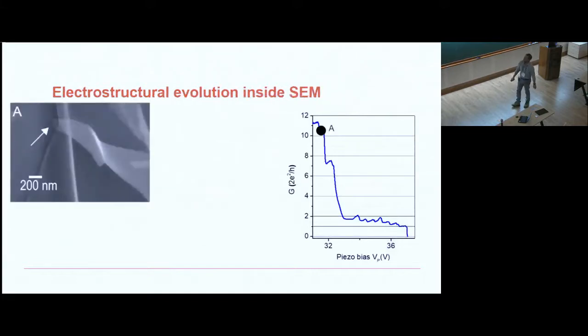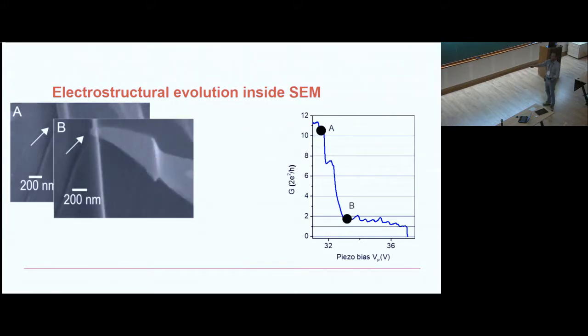For example, imagine this side is graphite, and on this side there's a metallic tip. What I'm doing is, I have banged the metallic tip on graphite, and I'm pulling it out. When I pull it out, I'm actually forming a very nanoscale bridge, which is connecting the graphite and the metal. And I'm continuously measuring the electrical conductance across this bridge, okay? So when the bridge is very thick, this is the point of contact. When the bridge is very thick, I get very large current, and the conductance of the system is very large. If I pull the tip farther up, then the bridge starts getting narrow before it ruptures completely from the graphite. Okay, and here is the narrow bridge.